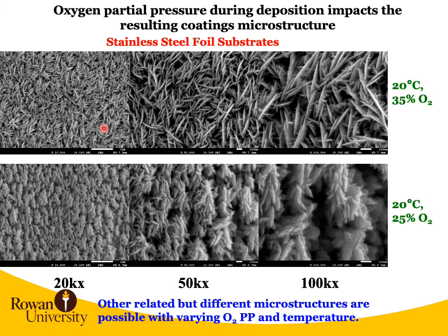Knowing that the microstructure changes as you reduce the oxygen partial pressure, maybe increasing the oxygen partial pressure will form those platelets. So we went ahead and did those measurements, and here are two representative samples. There are 3 different magnifications of each of these, and you see at 35% oxygen partial pressure in the sputtering gas, you see these sort of thin platelets on their edges that look like a very high density of what we saw in the earlier slide at 200 degrees C. If you go down in partial pressure, you see slightly different microstructures, but reminiscent of what happened at 35.